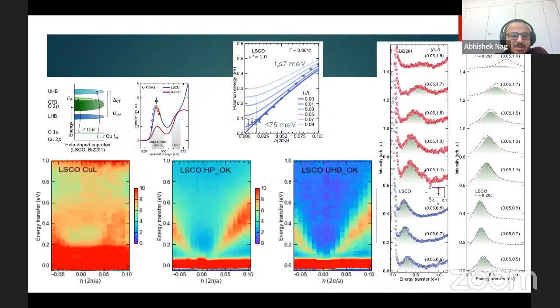So let me show you some other results. In the hole doped cuprates, we used this copper L edge data, exactly the same geometry. We find very faint excitations. If we had not probed the oxygen edge, it would be very hard to believe there is something really here. Why is it so? One argument is that because mostly the doped charges go and occupy the oxygen orbitals, it might be that the charges are more oxygen-like, but it's difficult to really understand because you have very strong copper-oxygen hybridization. We have also probed both copper and oxygen for the electron doped cuprates, and we find the plasmons in both copper and oxygen edges in the electron doped case. So those things have to be studied in further detail.